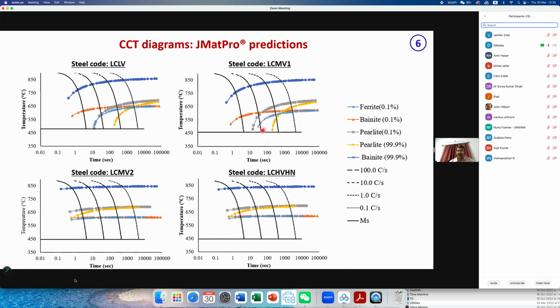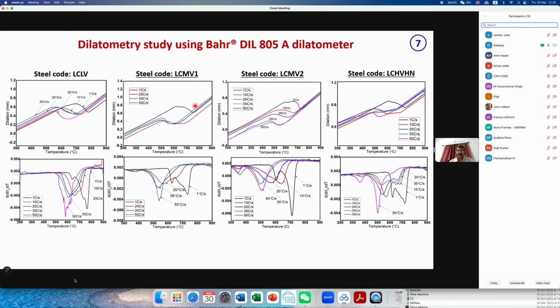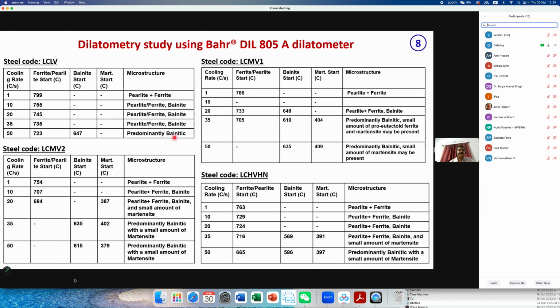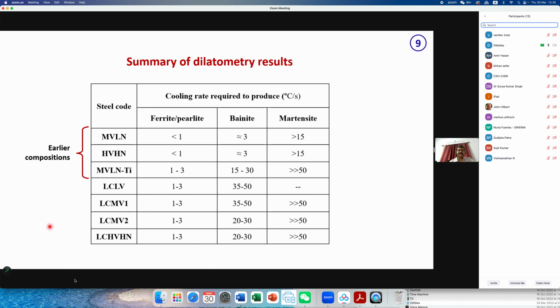We have done JMatPro calculation for kinetic prediction. We have done dilatometric study. These are the dilation curves for all the steels. So far, whatever we have made, we have performed a dilation study. We know the actual transformation start temperature for ferrite, bainite, and all those things, and martensite, for different cooling rates. We have varied the cooling rate from 1 to 50 degrees centigrade per second in our dilatometry study. This is the summary of all the dilatometric study of the vanadium grades that we have prepared.